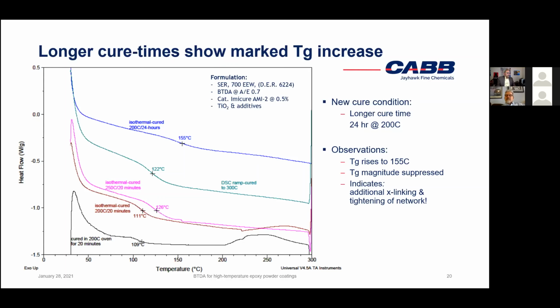Excellent point. So again, the key thing is that this was one particular formulation out of those 12 formulations you saw in that table. Here's the SER type epoxy resin, 700 equivalent weight, and one particular stoichiometric ratio, A over E. But everything you see here is just difference in curing profile. So obviously we saw that the TG is substantially increased from the original simple 20-minute cure cycle, from 109 to 155. That's pretty good deal, actually.